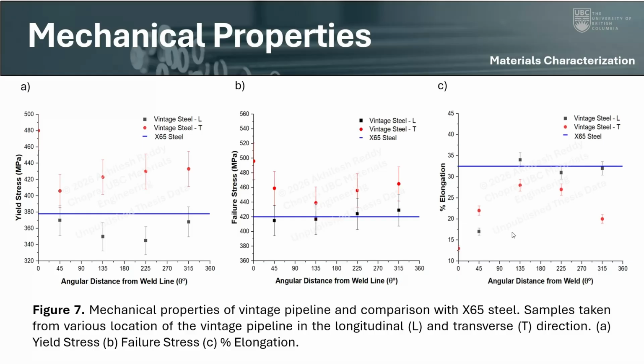On the x-axis, you'll notice the various locations along the circumference of the pipe, and then the data points. The red refers to transverse or perpendicular to the weld line, and the black data points refer to the longitudinal direction, along the weld line or parallel to the weld line. So what we can clearly see right off the bat is anisotropy, right?